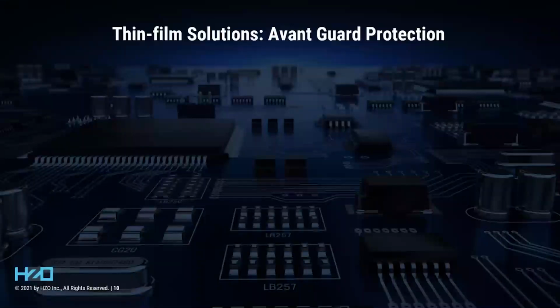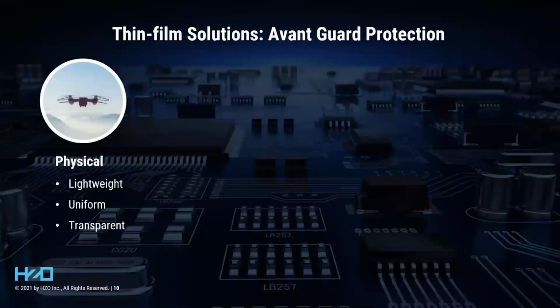So thin films, including Parylene and the range of chemistries possible with plasma and ALD, all have some broad features in common. Physically, they're thin. They provide equivalent protection to conventional coatings at less than 1/10 the thickness. Thin film materials are new to industry standards as a group, or at least to the ones that consumer electronics and industrial typically encounter. IPC, who handle a lot of the board manufacturing, many of you are probably very familiar with this group, only settled on their ultra thin, or UT, sub 25 micron material category in the last 5 years. Thin protection equals lightweight protection.